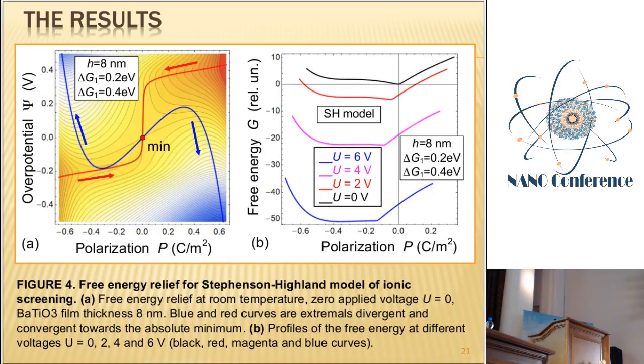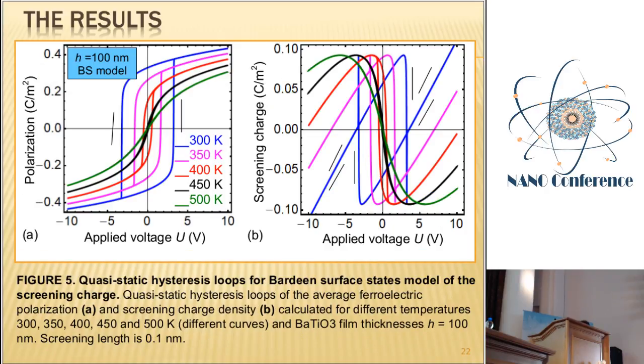For different formation energies, you can see that the extremals for one type of polarization become far from one another, and for other polarization directions, they become closer to one another. As a result, the potential has a linear part in the cross-section and a saturating well with a break between them. So in this case, one can expect an unusual shape of the hysteresis loops in the system. And let me show the loops.